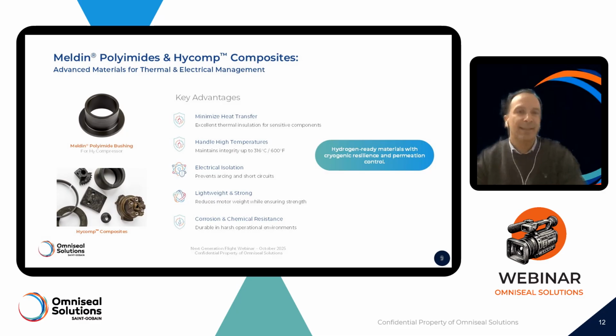the Meldin materials and Hycomp composites. Meldin is the brand name for our polyimide-based materials, and Hycomp composites are also polyimide-based materials, but they are reinforced with graphite, carbon, or glass fibers. Typical temperature ranges for the Meldin materials are from minus 268 degrees C up to 316 degrees C, with mechanical strength up to 40 megapascal and a low coefficient of friction between 0.12 and 0.20.